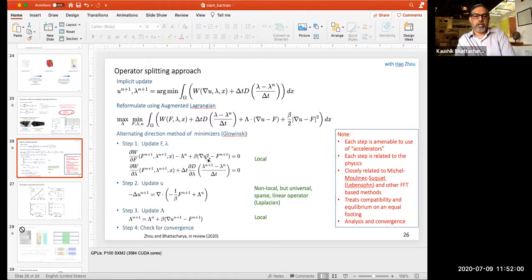Now, the other part here, which is slightly subtle, is because the solution to this is going to be the right-hand side of the Poisson equation, you really don't have to solve this to some L infinity norm. You only need to solve it for L^p norm. So even if there are some points which are not converging, you can actually move forward. So this becomes an extremely powerful numerical method. You can think of this as the constitutive relation. You can think of this as the compatibility equation. And it turns out that the convergence check also has a physical meaning as the equilibrium equation. So all of these things actually work very naturally when you do it this way.